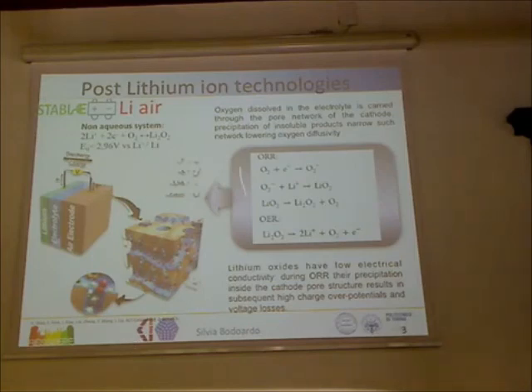But the species that reacts is the oxygen that goes in a conductive matrix, a system that is somehow similar to half of a fuel cell. So you have the oxidation reaction and the oxygen reduction reaction. Oxygen goes in this matrix, takes electrons, and forms an intermediate, a superoxide for instance. This superoxide then dismutates and forms lithium peroxide, that is the product of the reaction, and leaves oxygen away.